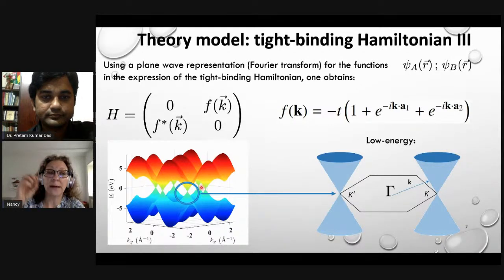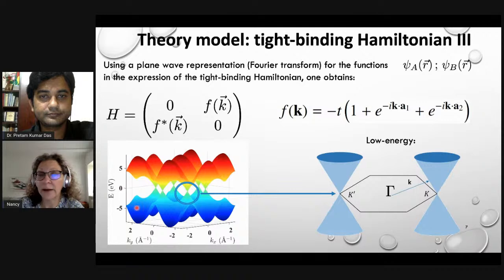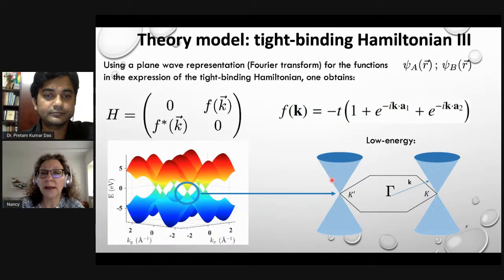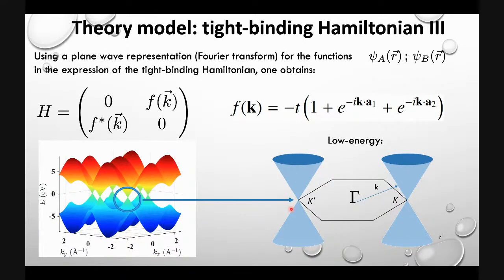And if we zoom in on what happens near these points, that is at much lower energies than 5 and -5 electron volts, if I look at what happens near this 0 energy, what I see is that the relation between the energy and the momentum is linear. These are cones. This is a conical dispersion in which the energy depends on the absolute value of the momentum. Now, from these 6 points that I mentioned, only two of them are completely different. You can think of these 2 points as representing in reciprocal space, in momentum space, being equivalent to the 2 sublattices that generate graphene in real space.